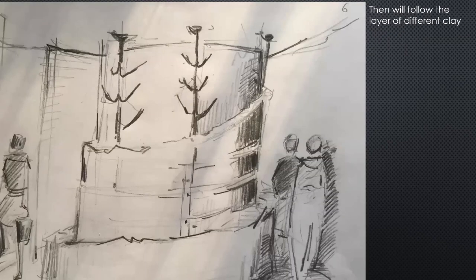Under the protection of the sails, the casting mold was built now. The first layer of finely graded clay was tempered with hair and well kneadable. The hair had another benefit. It burned when the form was fired, and the air could escape through the resulting small channels.